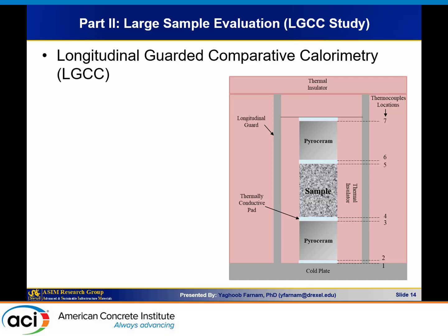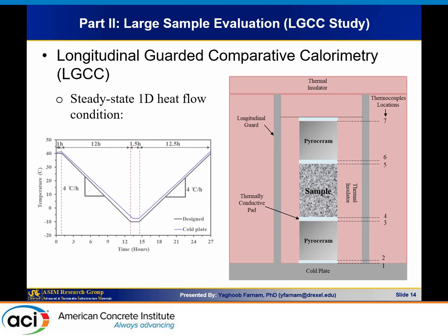And this is the work that we have done in collaboration with NIST, National Institute of Standards and Technology in the US. And the idea is that we want to have a steady state, one directional heat flow, so you could do some calculation to figure out the thermal heat release inside the sample. And then we want to be very slow. So here we're talking about degrees per hour. So we change 4 degrees per hour. So it's a kind of long process because we want to be in a steady state.